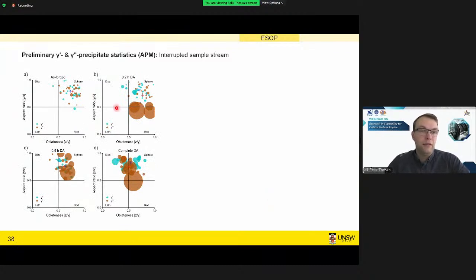We can have a look at the shape of these particles. So if we plot them for each aging step, we see they do start as near spherical particles, which then develop into these disks.